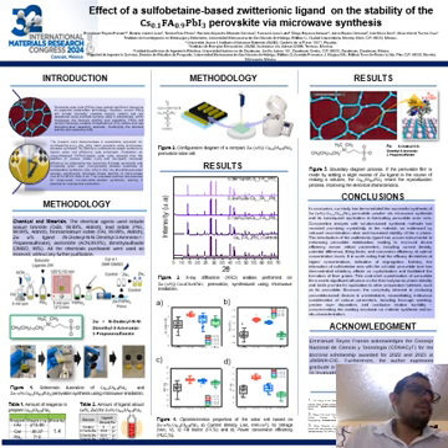It's worth noting that this efficiency diminishes at higher concentration, which is an indicator of segregation. So in this kind of work, we can use this additive of sulfobetaine ligands, for example, to test with another kind of perovskite, especially a lead-free system like tin-based. This kind of synthesis is interesting for large-scale preparation.